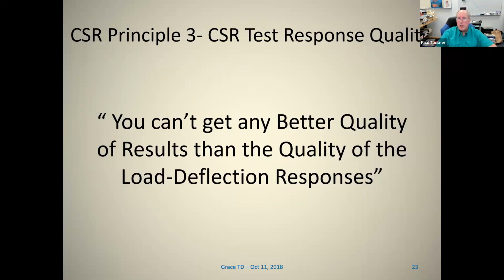The biggest thing about CSR testing is that you can't get any better quality of results than the quality of your load deflection curves. I've seen cases where the load deflection curves are really bad - not linear, with curvature, peaks all over the place. You can't trust things like that, and I'll talk about that later regarding the quality of the test system.